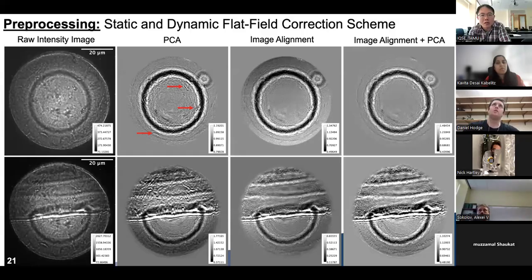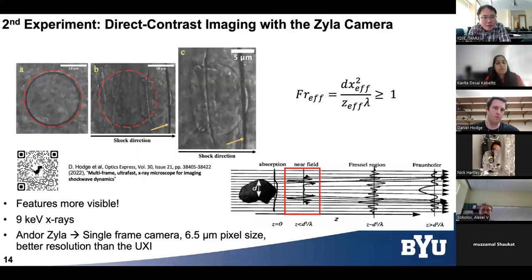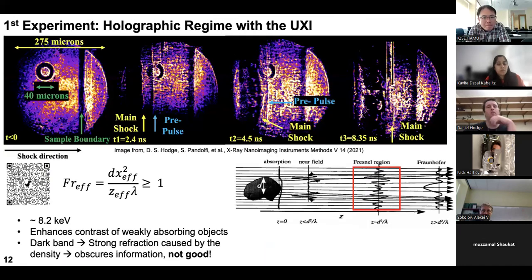So you're asking about the previous one, where you said this big dark region almost covers all the information. Yes, the dark band. From what we deduced, at lower energy the beam doesn't punch through this particular dark band because of strong refraction effects. But increasing the energy of the beam allows us to actually see these features.